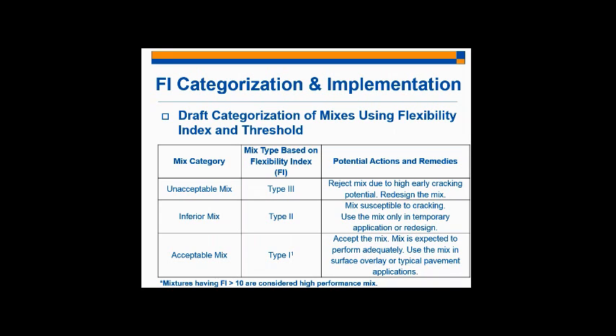If your mixture falls in the type 2 region, the mixture would be acceptable, but mediocre performing in terms of low temperature cracking resistance. And then the type 1 mixture is the acceptable, excellent performing mixtures, which can be used in surface overlays or typical pavement applications. We aren't considering structural or application variations in these mixtures. So I'm not saying that if you have a road with lower traffic levels, then you would take that into account as you decide to pass or fail the mixture.